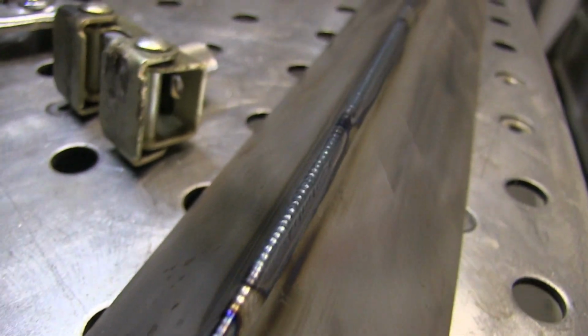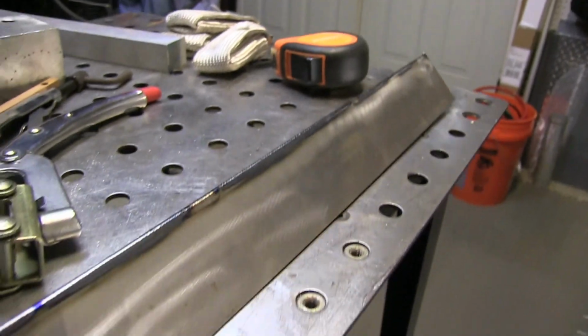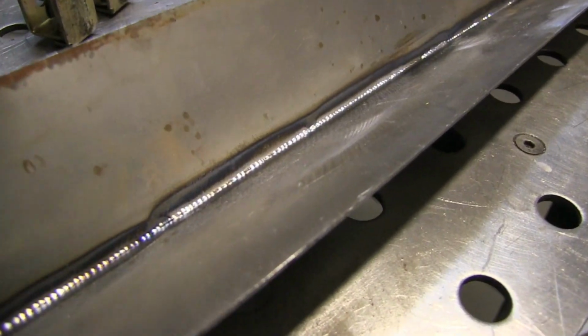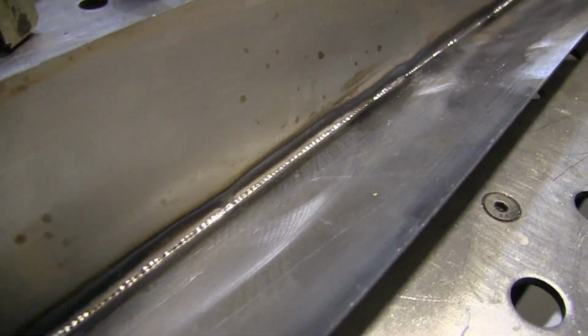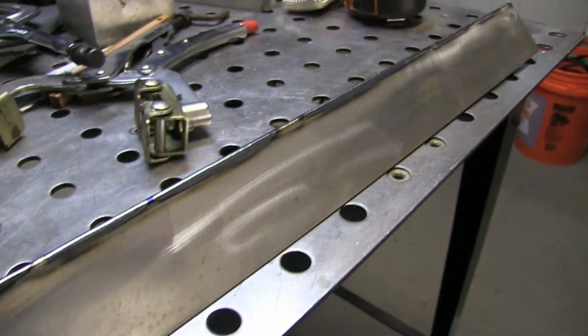Now, it's only 2 inches wide, so there's going to be a little bit of a bow to it. But if this had any stiffness to it at all, it wouldn't have warped much at all. And there's the inside. You can see it almost looks like there was argon on there with that aluminum chill. There's no magic pulse setting that's going to eliminate distortion. There's no magic welding sequence or technique that will completely eliminate distortion. Usually, you have to go to some great amount of effort on sheet metal. If you're doing something decorative, the expectation is that it's going to look nice and smooth, and instead it's doing this number, and you can tell everywhere you tacked it, it just wants to bulge and warp. Using chill blocks and backing bars is well worth the effort.